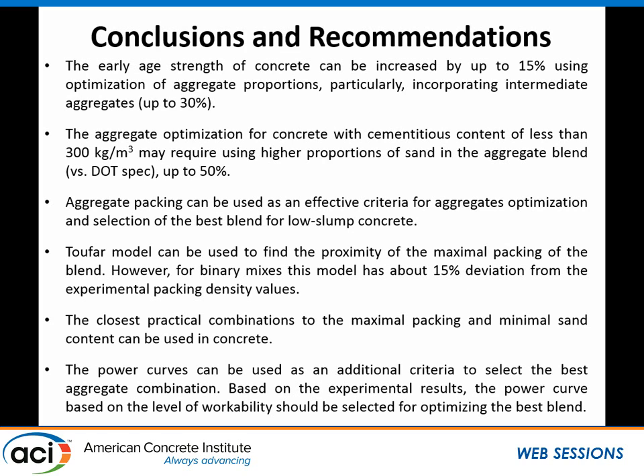Aggregate packing then can be used as an effective criterion for aggregate optimization, especially when you're talking about low slump, low cement content concrete. The models can be used versus experiments, but you have to be careful about where your maximum packing is happening, at what fine content, and how far you are off from the experimental packing. And then you can use continuous gradings, but you have to know what power curve it is. Is it 0.45? Is it 0.35? It depends on the application, as Eric mentioned before. And then you have to know the deviation from that grading. And you have to play with your aggregate blends to figure that out.